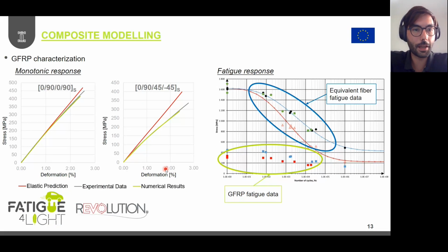And for example, by applying this homogenization serial parallel rule of mixtures within the Fatigue4Light project, we have several pretty complex composite materials. For example, on the left-hand side chart, we have a composite material formed by, I think, 8 layers, because this is the denomination of the symmetric part. So we have one layer at 0 degrees rotation of the fibers, then another layer of 90, 0, 90, and then it's symmetrical. And since those cases were tensile, even with one finite element at constitutive level, we can homogenize the behavior of those layers.